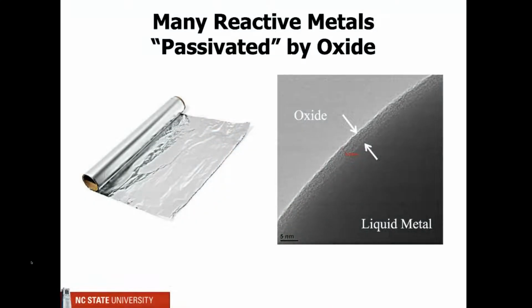So it's only a few atoms thick, but it's important because it has a big effect on the way this stuff behaves. Now this is not really all that surprising because actually, believe it or not, the aluminum foil that you have in your house also has this, because remember it's a brother with gallium. And this is really important because if aluminum didn't form this, aluminum is actually explosive. Did you know that? You had explosive materials in your kitchen and you probably cook with them. So this layer, we call it passivating because it's like a shield. The oxygen's over here, the metal's over here, and it protects it.